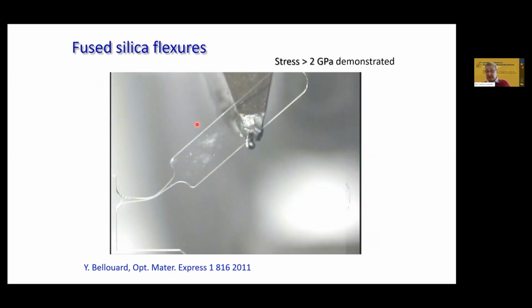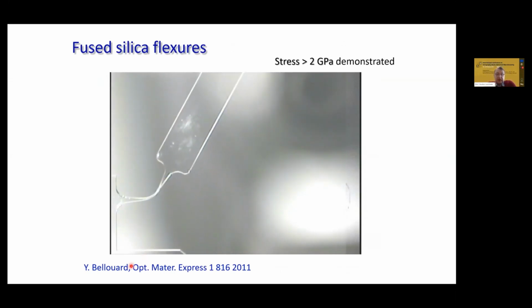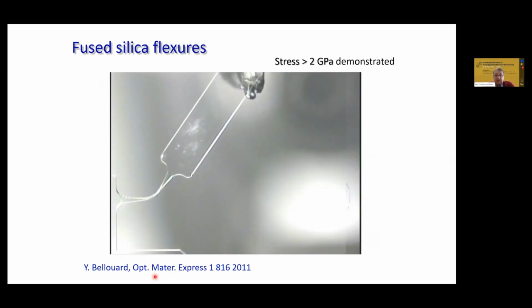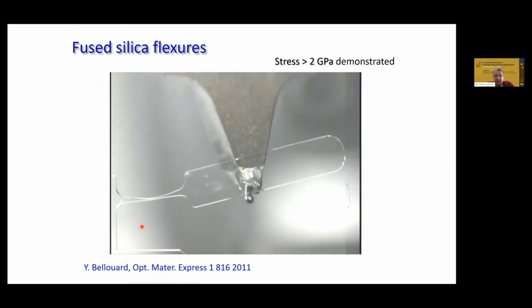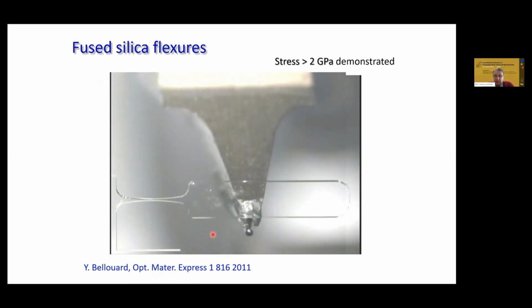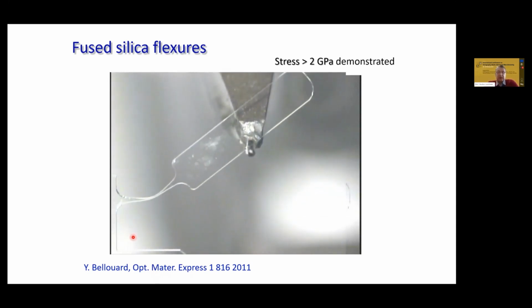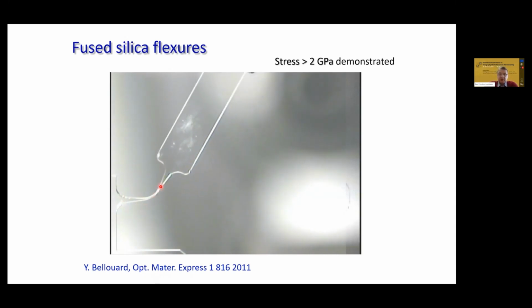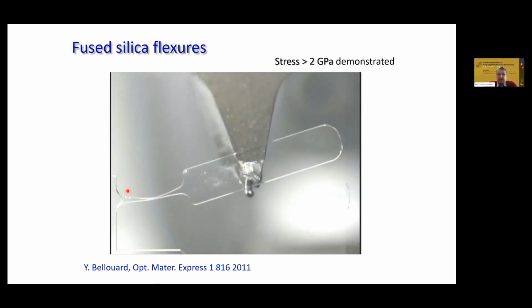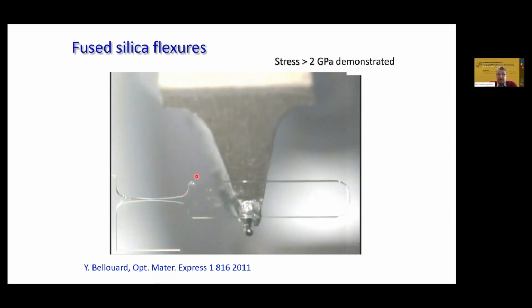So the same can be done in glass. And this is another example from a colleague's lab. Bellouard is cutting glass using a femtosecond laser and etching, and he is interested in mechanical properties of those glasses. You can see that etching removed all the stress, all cracks are removed by etching, and this allows you to reach almost the limit for silica glass in terms of stress. It can withstand 2 gigapascal stress without breaking.